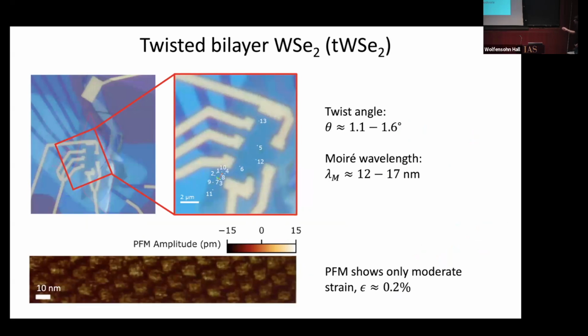So here again is our sample. This one isn't quite as homogeneous. The twist angle varies between 1.1 and 1.6 degrees as we explore different parts of the sample. That translates to a Moiré wavelength of about 12 to 17 nanometers. So although the twist angle variation is relatively small, actually this is a factor of 1.5 in Moiré wavelength, so it has a pretty profound effect.